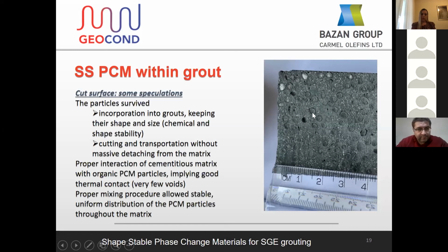You should understand that these particles within this grout survived contact with quite aggressive components of the cementitious grout, a very alkaline medium, and they stay inside the matrix even after cutting it and transporting it. So this implies that there is good thermal contact of PCM with the grout. This way, the PCM demonstrated its chemical resistance, shape stability, and sufficient mechanical strength.